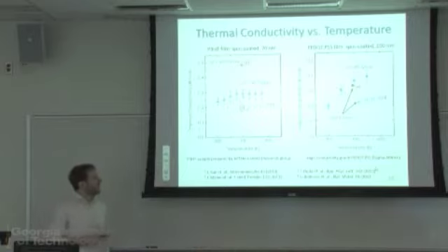The only other temperature-dependent measurement of PEDOT:PSS is much flatter, not showing the same dramatic temperature dependence, although they also didn't go to lower temperatures. So it's hard to say whether their behavior is the same or different because they measured a very narrow temperature range. It's likely that there is some other contribution to this change in thermal conductivity besides what you normally see in an amorphous polymer system. But we really have to investigate this more to understand what it is.